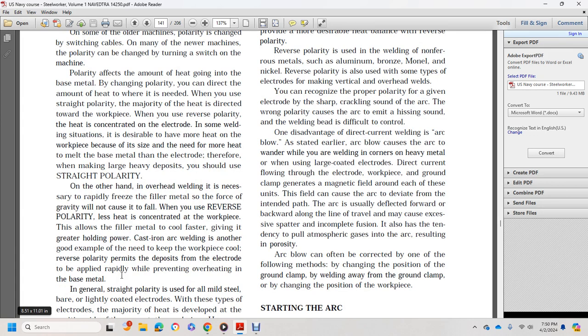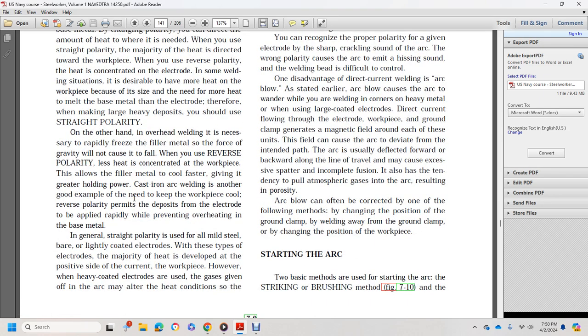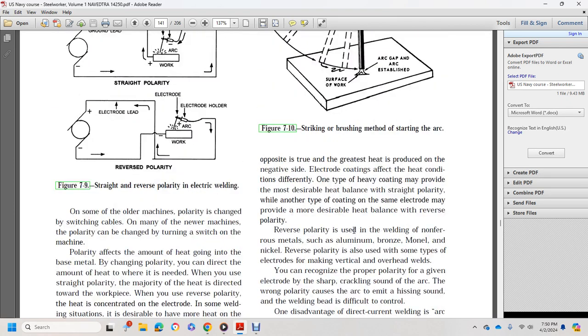Cast iron welding is another good example of the need to keep the workpiece cool, as reverse polarity permits the deposit to be applied rapidly with an electrode while preventing overheating of the base metal. Generally, straight polarity is used with all mild steel with fairly light coated electrodes. With these types of electrodes, the majority of the heat is developed at the positive side of the current, the workpiece. However, with heavy coated electrodes, the gases given off within the arc may alter the heat conditions, so the opposite is true, with the greatest heat produced on the negative side. Electrode coatings affect the heating condition differently. One type of heavy coating may provide the most desirable heat balance with straight polarity, while another type of coating on the same electrode may provide a more desirable heat balance with reverse polarity.